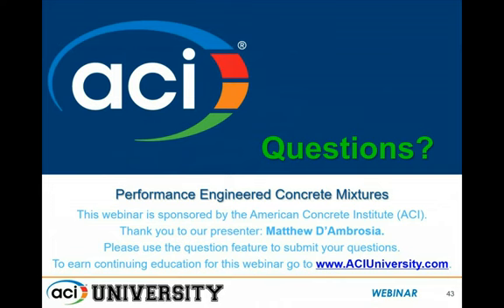These material developers have already spent some time looking at this ring test method as well. And the best thing you can do, if you're either on the construction side or you're on the specifying engineering side, is ask for data. Ask your material suppliers if they've run the ring test. And if they can provide you ring test results that show 28 days or more of crack resistance, you're in really good shape, I think, for many structures in having a good crack-resistant material.